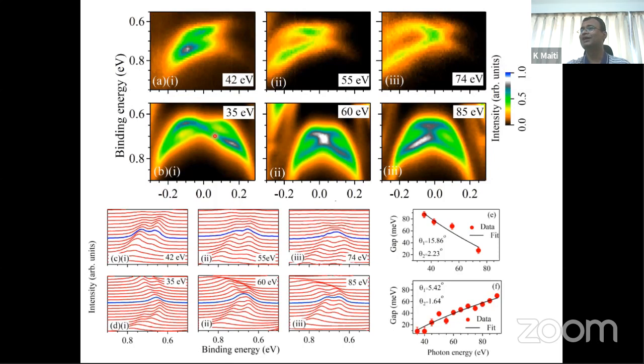So now what we have done is that in this case, we have optimized the experimental conditions at 35 eV and done the experiment. This is done at Diamond. And you see that this is the EDC corresponding to this color plot, and as you go to higher photon energy, a gap opens up, okay, which is plotted here. So you have a zero gap, and then it increases if you increase the photon energy.